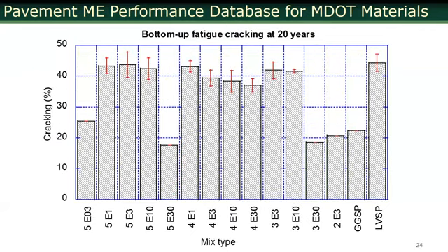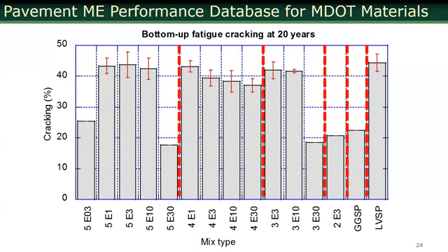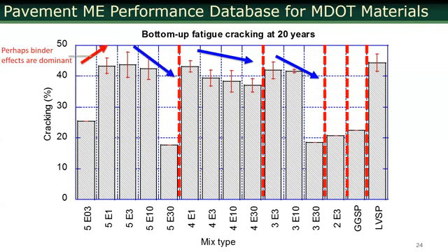I'm just showing that you can do stuff like this to see the effect of different materials on compaction level. This is the cracking, with similar results: cracking decreasing with higher levels of traffic, and decreasing again here. Not much difference between these three, but significantly lower cracking for 5E30. So we've seen similar results here.